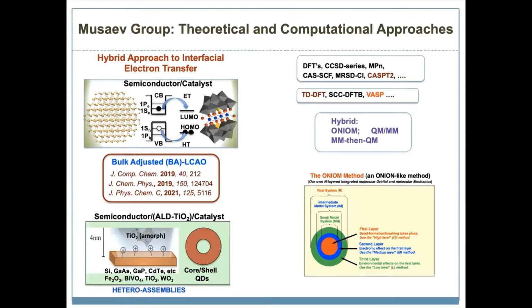Or I'm sure you are familiar with the technology called atomic layer deposition. You put the sensitizer or catalyst on the electrode, and if its stability is not very high, then people put on top of that this atomic layer deposition type of technology, using additional materials to keep the electrolyte stable. But when the electron transfer takes place, these materials deposited into the electrolyte also impact electron transfer processes. Unfortunately, these heteroassemblies were not suitable for theoretical approaches. We've been developing these additional theoretical methods.